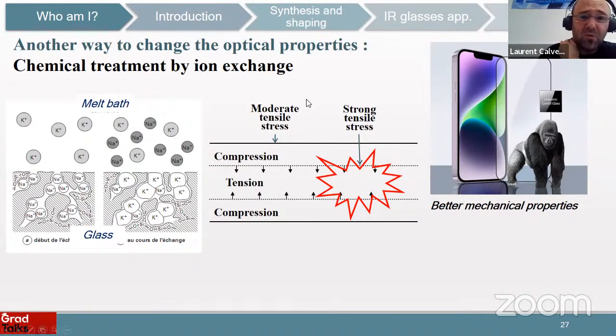How is it made? It's a simple glass, but they have improved its mechanical resistance by chemical treatment using ion exchange. It's pretty easy to understand how it works. What they've done is to take a glass like this one, which is based on silicate, oxide, and sodium, and put it in a melting bath based on potassium nitrate. After several hours or days, potassium, which is bigger than sodium, will enter the glass, and sodium will go out. So when you put something bigger in a glass, you will have a compression layer on the top and some tension inside. And when you do this, you have strengthened the glass and obtained better mechanical properties.